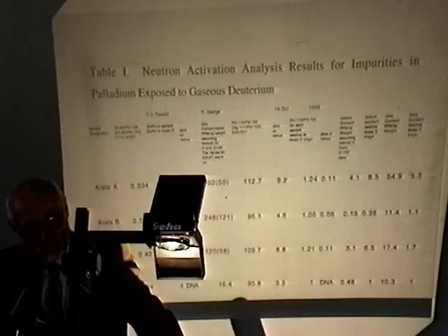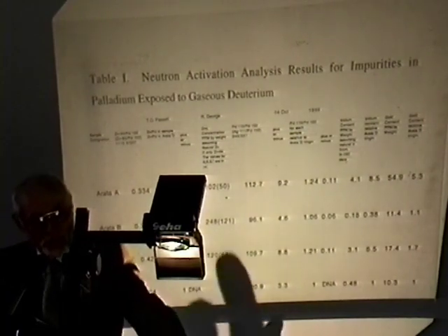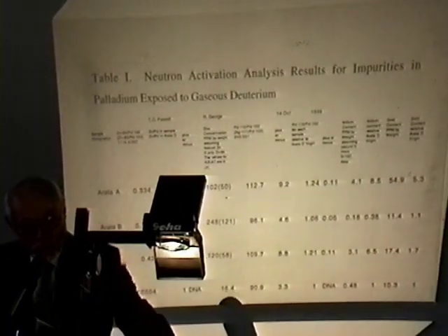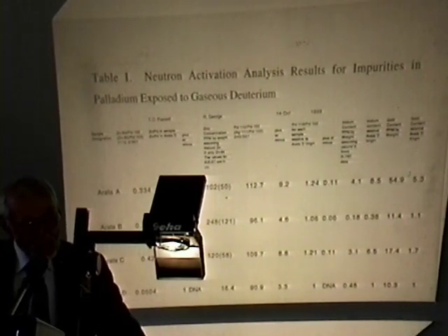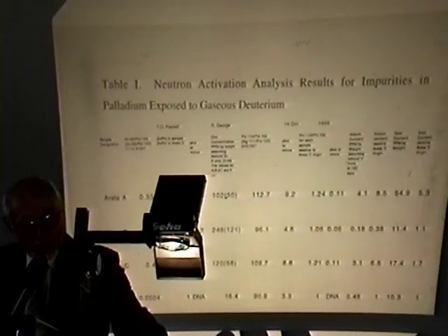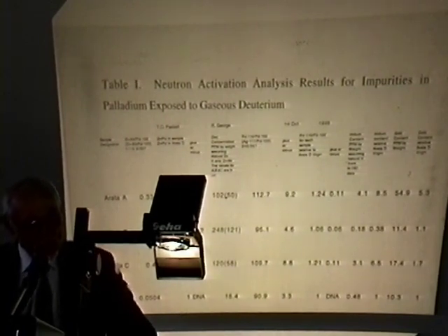The only thing I measure is zinc 64, and I'm inferring these numbers would be true if we had natural zinc. But if we have just zinc 64, the parts per million by weight would be these in parenthesis. And I assume the virgin is natural zinc. In any case, we have factors of 8, 14, and 7, roughly, increases as a result of them being exposed to fairly high-pressure deuterium in the center of those cathodes for the order of months.